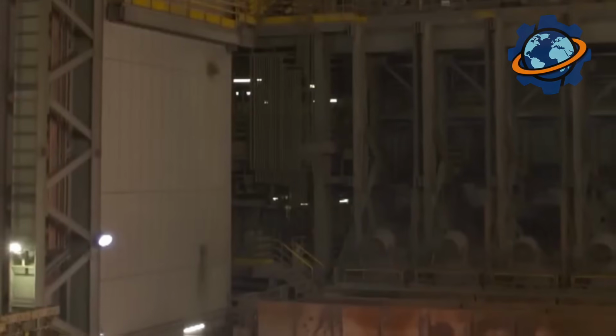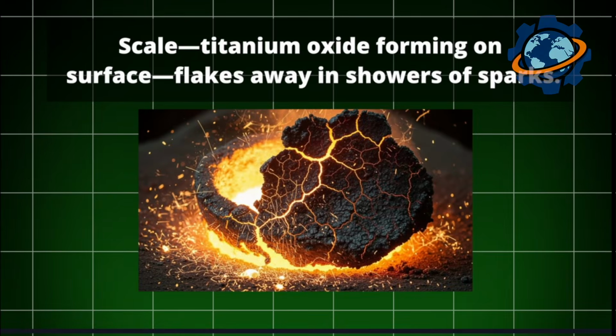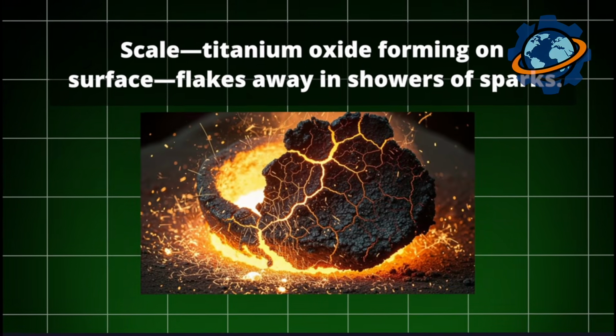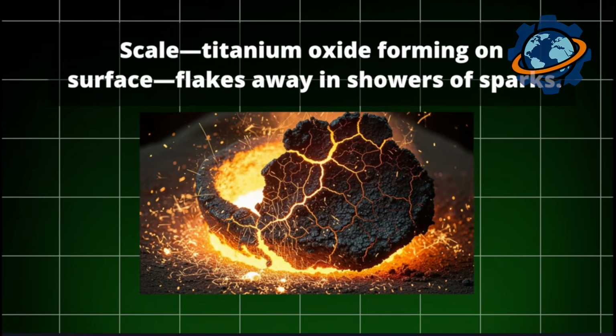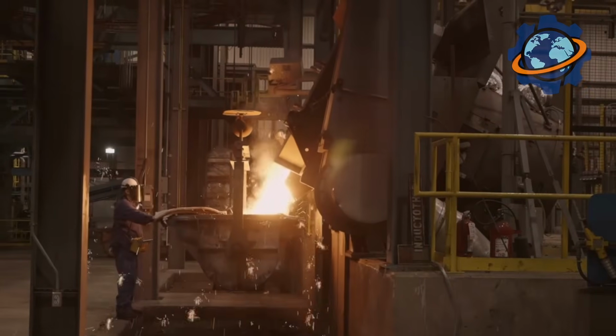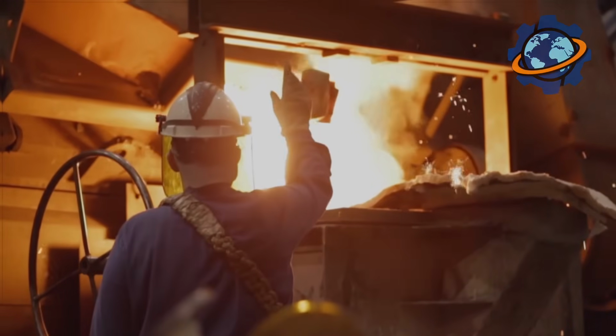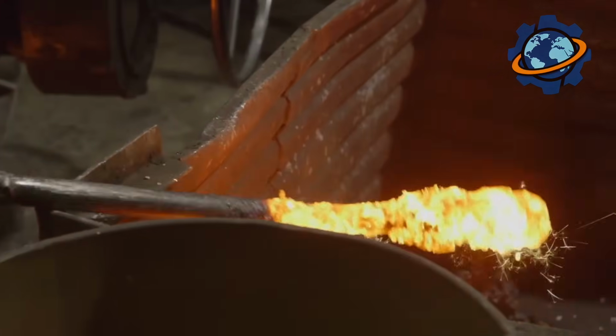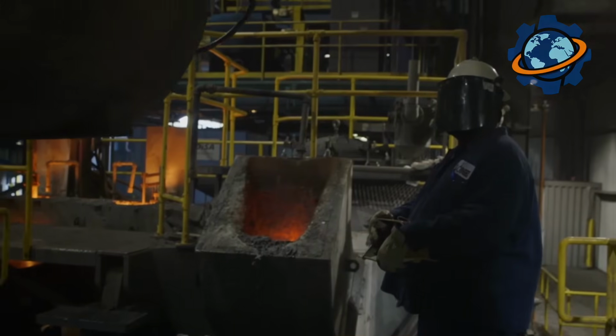Watch the titanium emerge, a glowing ribbon extending at 15 feet per second. Scale, titanium oxide forming on the surface, flakes away in showers of sparks. Workers monitor thickness using laser micrometers accurate to thousandths of an inch. Any deviation triggers automatic adjustment. The plate exits at quarter-inch thickness, cooled via air blast to 800 degrees before transfer to the finishing area. This single rolling operation produces material worth $2 million per batch.